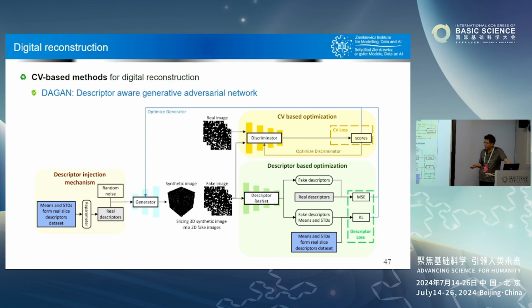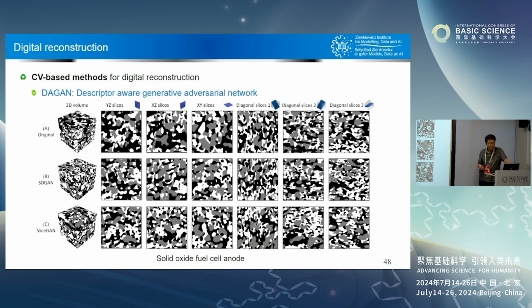What we did here is we introduced descriptors as part of the discriminator. So there are 2 parallel discriminators. One is the traditional discriminator, which only considers the image as the input, the fake images, and for the other one we consider descriptors. These combined together compete with the generator. So it's like the traditional GAN model, where you have 2 neural networks fighting against each other. Now we have 3, 2 on one side, 1 on the other side. And the result is very encouraging. It is, I'd say, at least one order of magnitude faster than the standard GAN model without the guidance of descriptors, and the accuracy is far better.